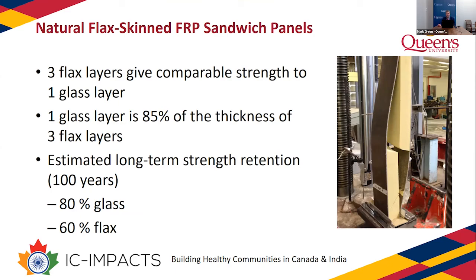And they found that the structural effectiveness of 3 flax layers was comparable to 1 layer of glass. But it actually turns out that the 1 glass layer was also approximately equal to the thickness of the 3 flax layers. Additionally, they looked at the long-term strength retention, and at 100 years, they found that for glass it was 80%, and a bit lower for the flax at only 60%, but still very promising for the technology.